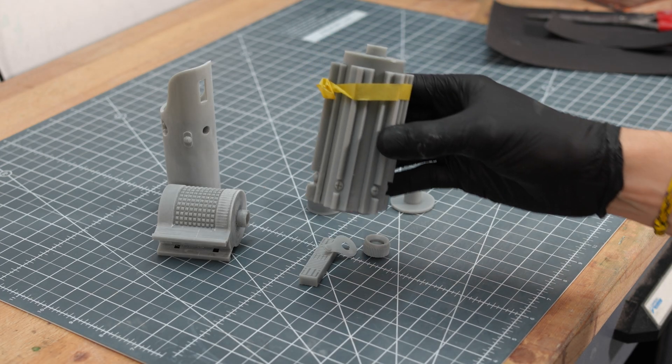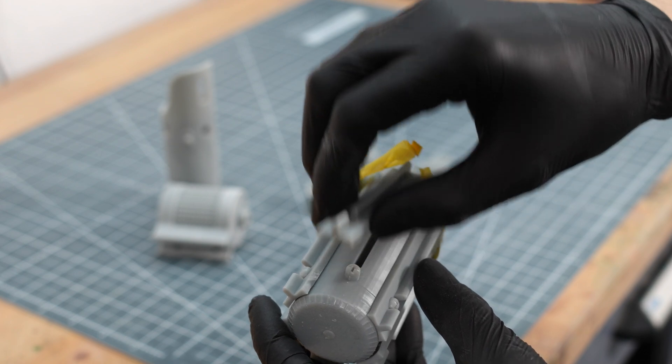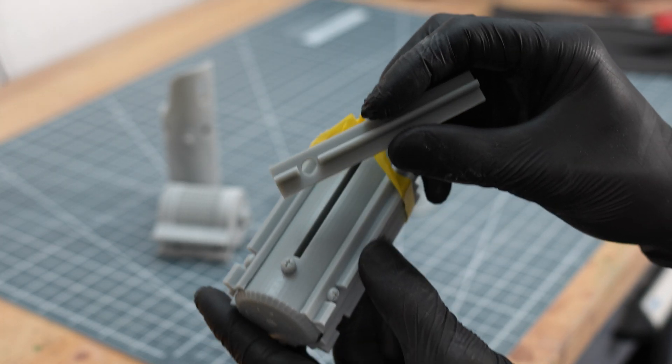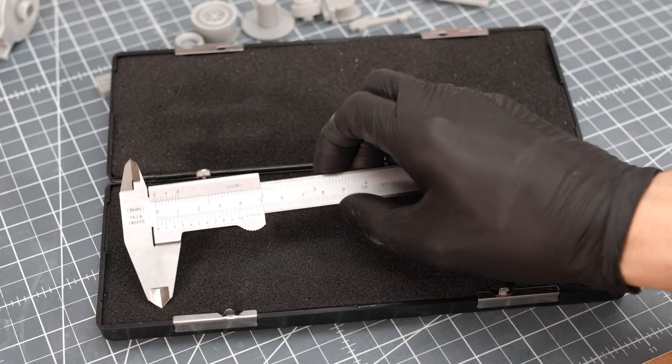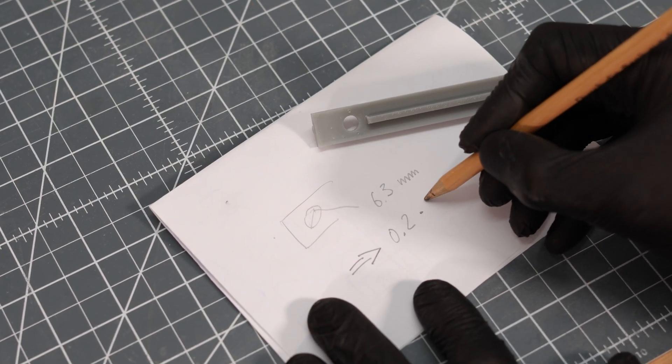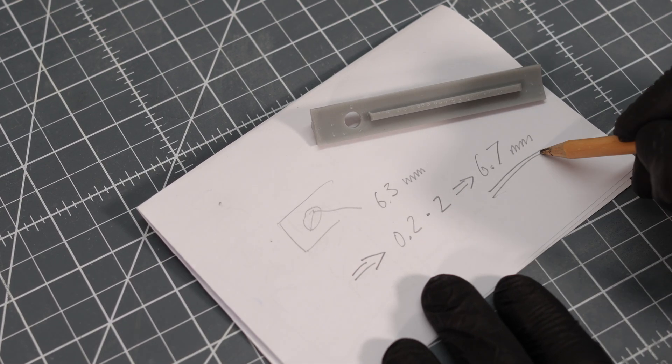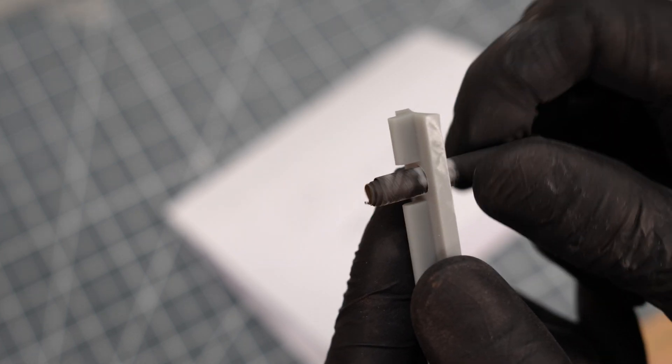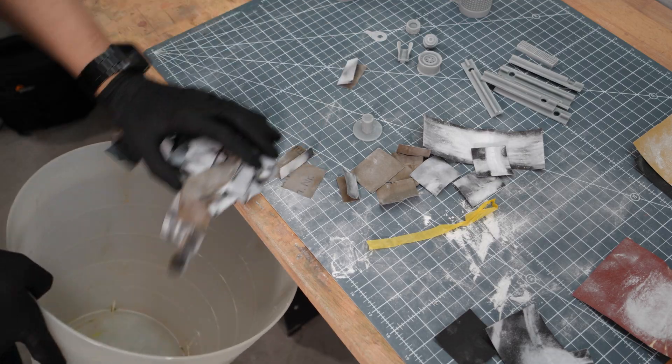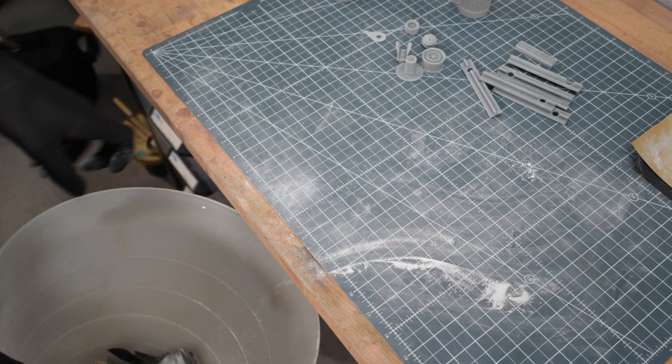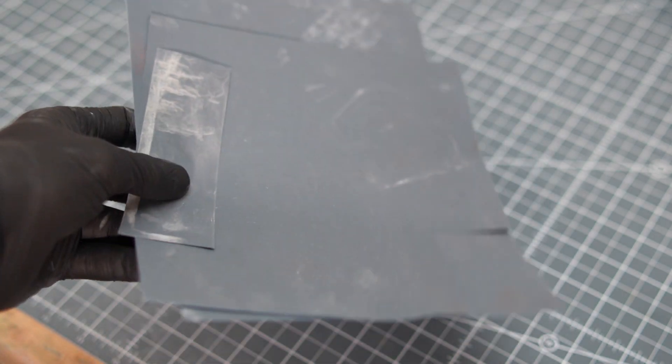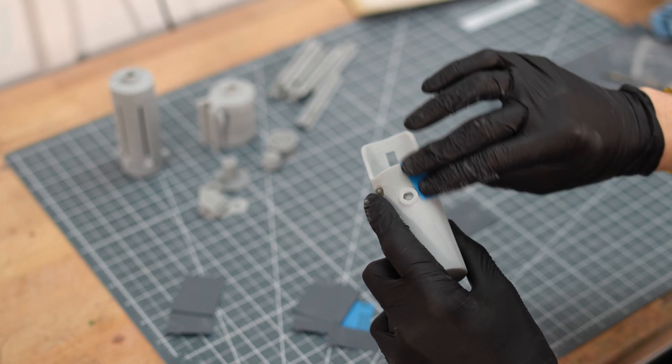Regarding clearance, some parts are assembled very tightly together. It's essential to know that the applied copper thickness should not be neglected. Therefore, I measure and calculate how much space I need to leave between the components. As a rule of thumb, I always assume a 200 micrometer layer. I file and widen the parts to the correct size. Try to bind the dust and keep the work area relatively clean, to start round two with even finer sandpaper.